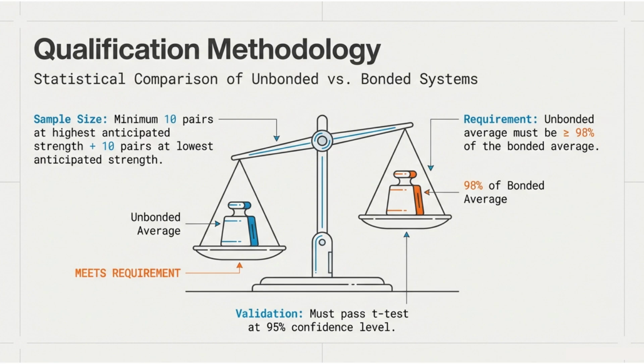Now let's discuss how qualification is actually done. This slide shows a statistical comparison between unbonded system average and bonded system average. The sample size requirement shown: minimum 10 pairs at highest anticipated strength, plus 10 pairs at lowest anticipated strength. So we are not just testing one cylinder. We are testing a meaningful set so we can prove consistency. The requirement shown is unbonded average must be greater than or equal to 98% of the bonded average. That means the unbonded method cannot systematically underreport strength. And validation must pass a t-test at 95% confidence level.